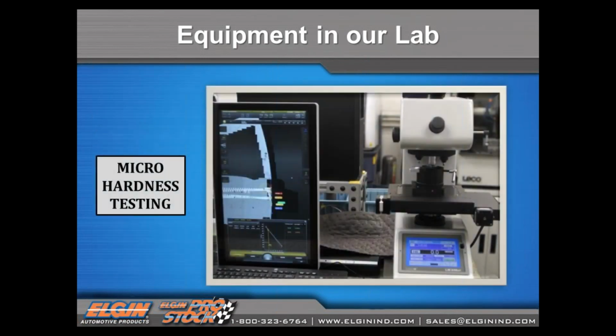We didn't talk about micro hardness testing, but when we were talking about case depth, cases are spec'd to be a certain depth and a certain effective case. Like I said, they want a hardness of 50 at a certain depth. You say, how do you know that? Because if I throw it on my Rockwell C tester, I'm just seeing what the surface is at. Or on a lighter scale, because it's a thin case, I don't want to punch through it. I don't know how much of that case I've got.